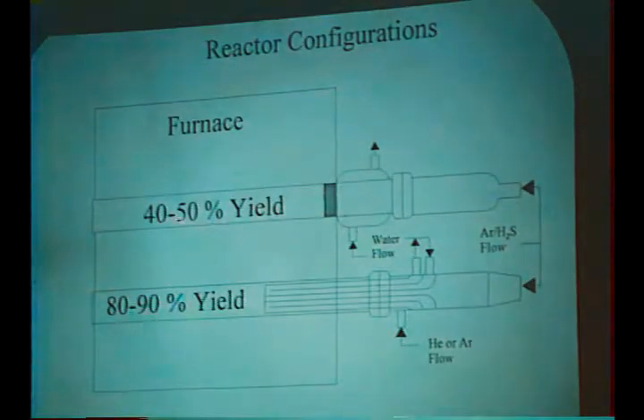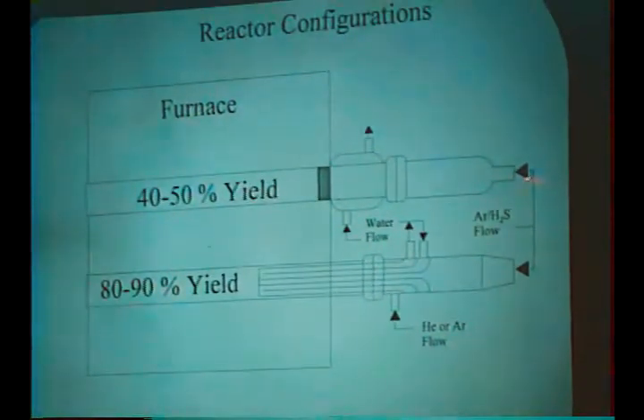When I initially began these syntheses, this is the type of reactor that I used, essentially the same one you saw in the previous slide. Essentially, what we have here is a water jacket that allows you to maintain a constant temperature into the hot zone. The problem with this reactor is that we accumulated large amounts of metal. As the metal carbonyls decomposed, they accumulated on the inner surface of the reaction tube. So I modified the reaction tube to increase the yield, and as you can see, it increased it significantly. Basically, what we have here is a water-cooled injector. The material goes here. You're able to maintain control of the temperature into the hot zone. The material shoots into the hot zone, is decomposed, and then is collected. There essentially is no collection of material at this point. And as you can see, the yields have essentially doubled by this modification.